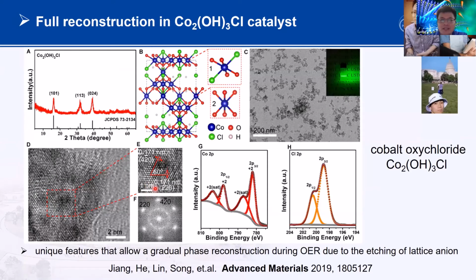This is just a change at the surface, because this is a layered material and the electrolyte has a hard time reaching the inside. So in that case, we synthesized another model catalyst, which we call cobalt chloride hydroxide. Before the reaction, you will see clearly the atomic structure: cobalt bonded with 4 oxygen and 2 chloride, so a coordination number of 6. In this material, only 2 oxygen are replaced by chloride. This is HRTEM to confirm the structure, and this is XPS, which shows the valence state of the cobalt and chloride. So this clearly shows the material.